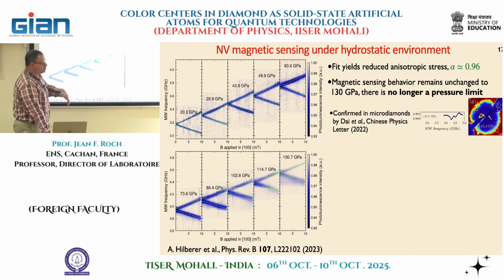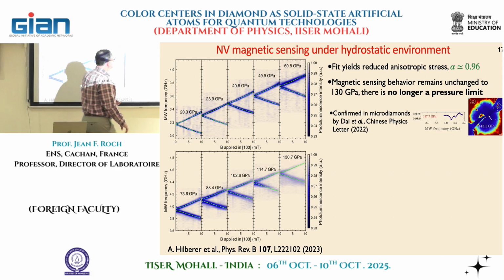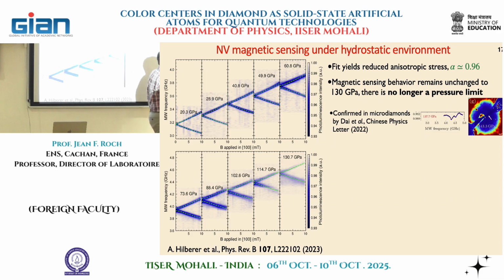And this is now what we're trying to do. It was confirmed in microdiamonds, by putting microdiamonds inside the sample, with the signal that was observed at that pressure, but perhaps not as convincing as the one we had. But nevertheless, it was also an independent proof.